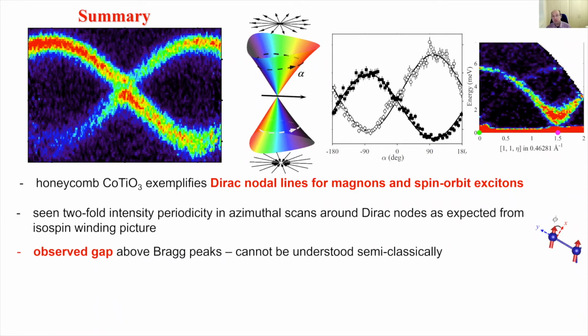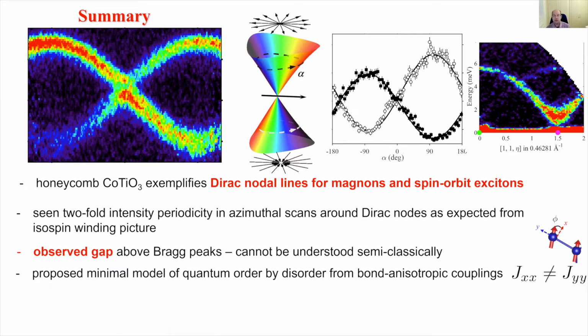And one aspect that was quite surprising to resolve in the experiment was the presence of a gap above the magnetic Bragg peaks, which indicates a preference for certain discrete directions in the plane. And this cannot be understood semi-classically. We've discussed two possible scenarios to explain this. One involves quantum fluctuations. There is a contribution to the ground state energy from zero-point quantum fluctuations, and some directions could have higher zero-point energy gain than others, and that could provide a mechanism for this.